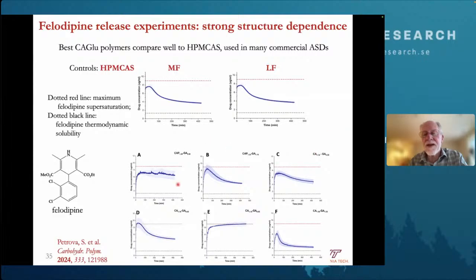And these bottom curves, A through F, are different cellulose acetate glutarates, cellulose acetate propionate glutarates, with different degrees of substitution. One of the things all of this work tells us is that these polymers are exquisitely sensitive to the degree of substitution and the type of other substituent that's on there. In other words, we can really design for performance.